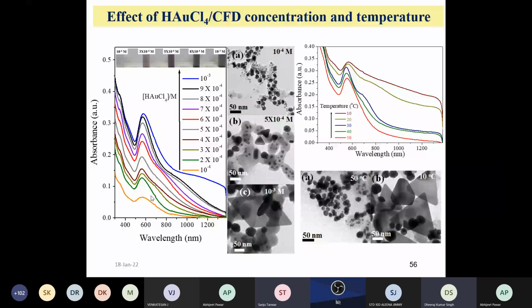And immediately if we take the transmission electron microscopy image of a particular area, you can correlate UV and TEM. Suppose this is 10^-4 molar concentration, and here also 10^-4 molar. If you compare, spherical nanomaterial will be there. And if you change the concentration, increasing from 10^-4 to 10^-3 molar concentration, anisotropic nanomaterial appears.